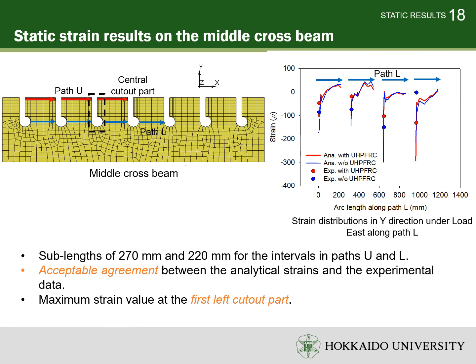From the literature, the rib to deck weld joint and the edge of circular shape cutout are the critical locations under severe stress concentration in the steel bridge deck. Therefore, the strain results at these locations are also examined along path U and path L in the middle cross beam as shown in the left figure. The U and L paths are divided into 3 and 4 intervals with a sublength of 270 mm and 220 mm respectively. The right figure shows the vertical strain distribution under load east along path L.